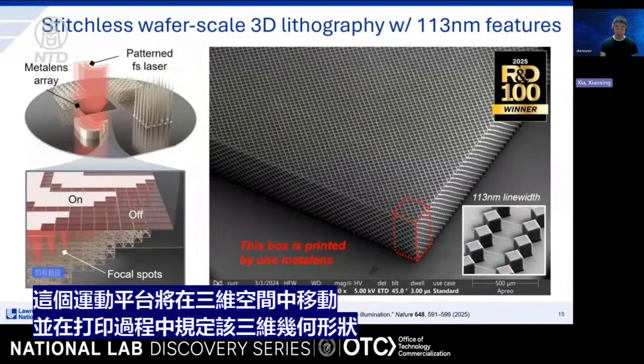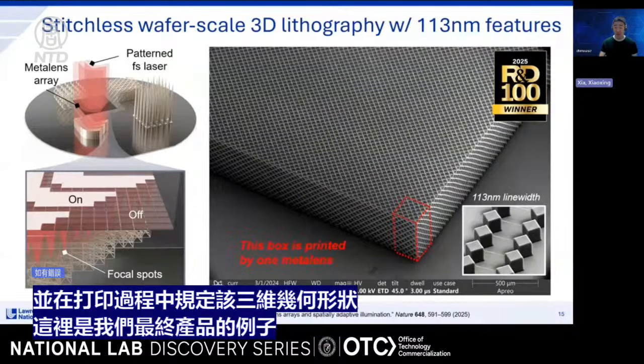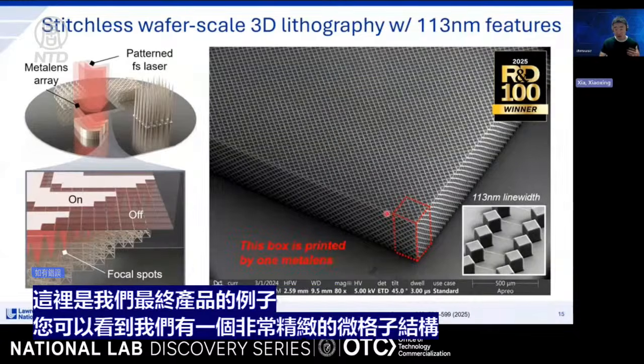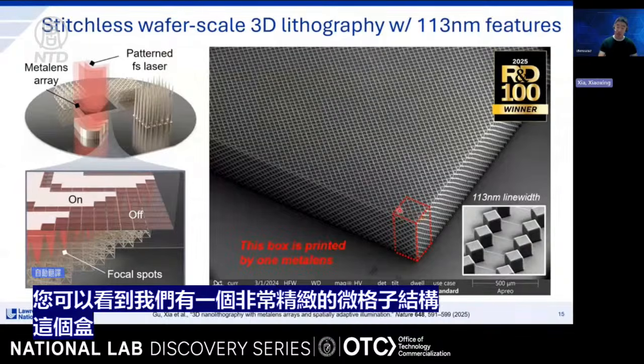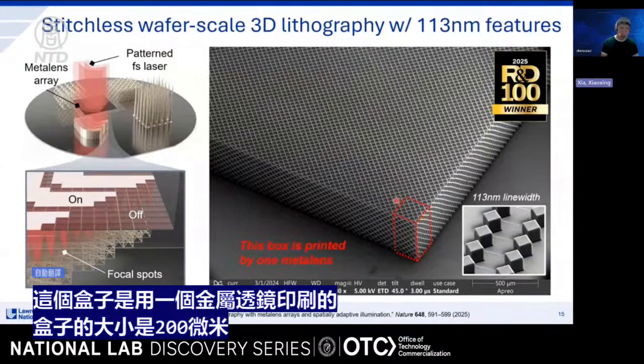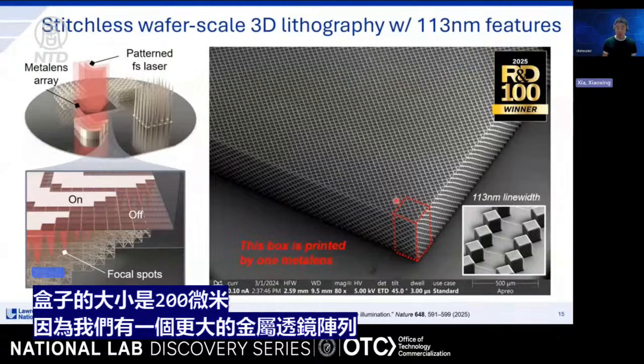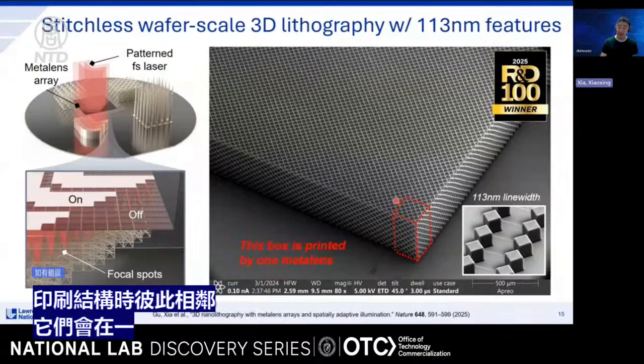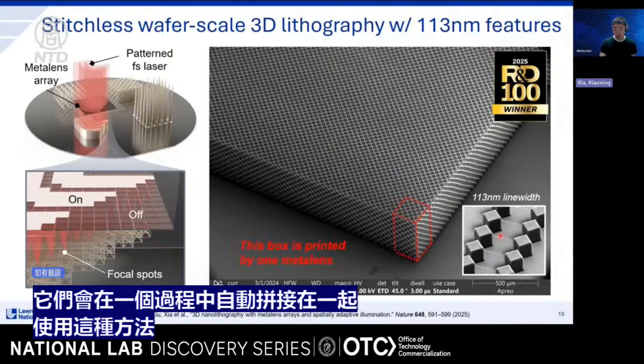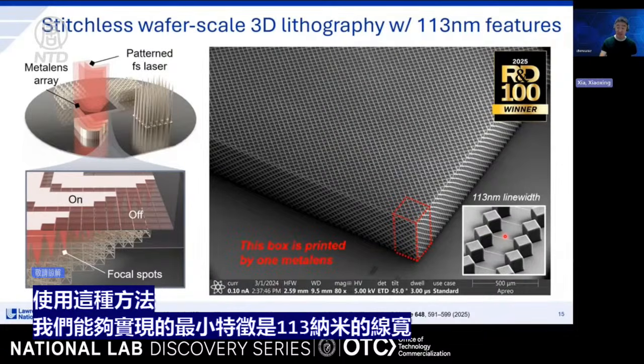And here is an example of our final product. You can see here, we have a very intricate micro lattice structure, and this box is printed with one metalens. The box is 200 microns in size. And because we have a large array of those metalenses printing structures next to each other, they will be stitched together in one process automatically. And the minimum feature we can print using this method is a 113 nanometer line width. And this technology, last year, just won the R&D 100 award.